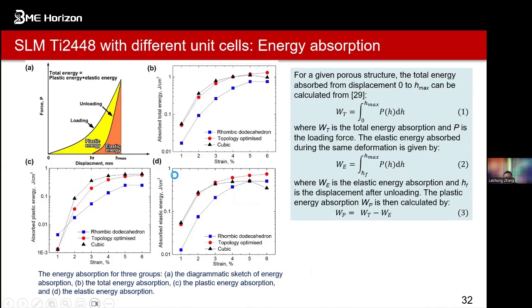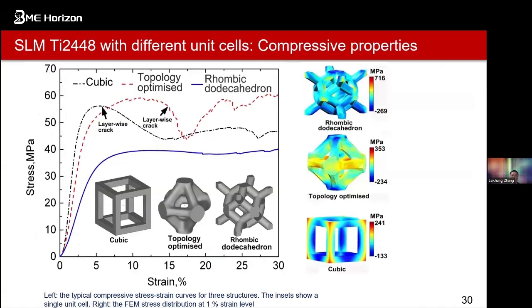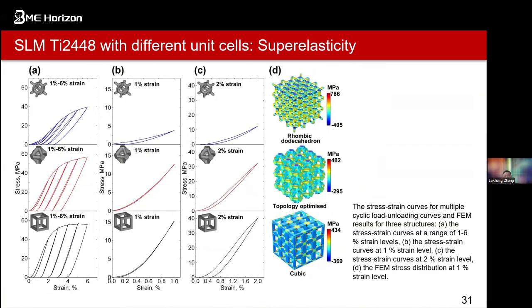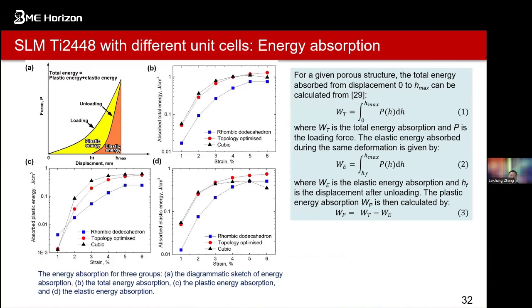So now from here we can get the information. We can get the parameters in different ways. We can get the data for the total energy. Total energy is because of the elastic deformation and also the plastic deformation. So of course, from the curve, this one is higher and larger, so it has more total energy because of the elastic and plastic deformation, because of the high strength and the large ductility. But we must care about the elastic energy, because this is energy absorption. You can see the topological one will be large, so it has large elastic energy. So that's why it's good as a replacement for these things.